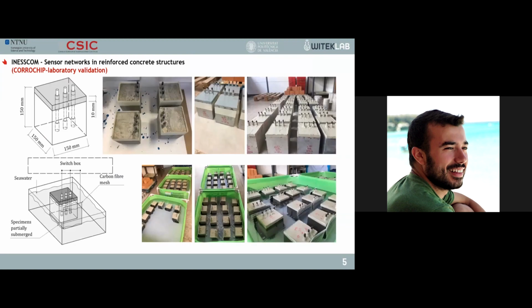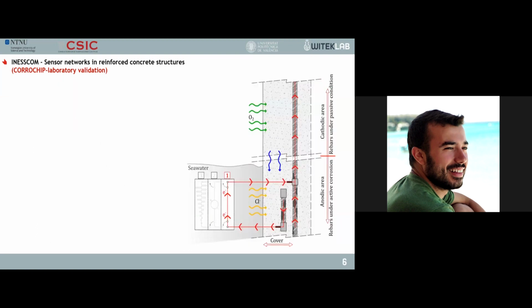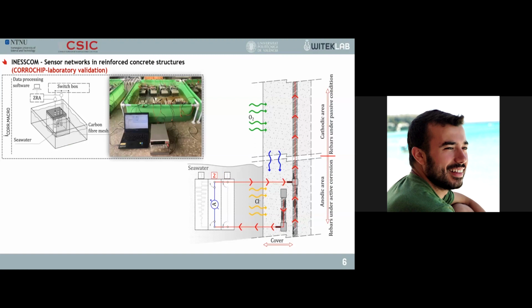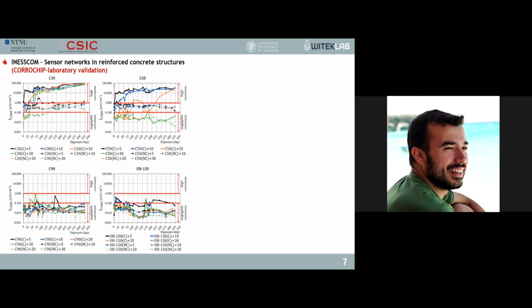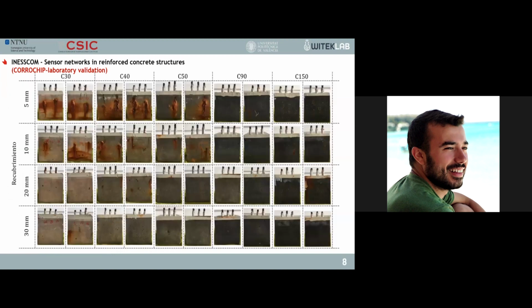Correct? The validation of this corrosion monitoring method was carried out on specimens manufactured with 5 different concretes. As you can see, they were partially immersed in seawater. For 1 year, corrosion monitoring was carried out using the methodology described previously. Periodically, macrocell currents were analyzed, and then microcell corrosion analysis was performed. Here you can see the results obtained for some of the test specimens. I'm not going to describe them in detail, but I will leave a link at the end of the presentation to the manuscripts where the results were published and described, in case anyone wants to know more about this study. I will focus on the validation.